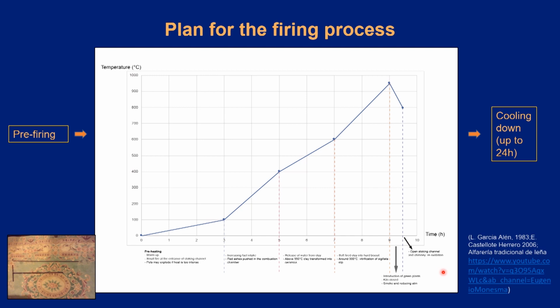When the temperature is below 800 degrees, the stoking channel and the chimney will be opened again to produce reoxidation. As a result, unpainted pot sections will become red again, but those areas covered with sigillata should remain black, as sinter sigillata should retain the carbon molecules. Lastly, we will leave the kiln to cool down slowly by sealing the chimney and the stoking channel with bricks and clay. This stage must last at least 24 hours and always be monitored by thermocouples before opening the kiln at temperatures below 100 centigrades.